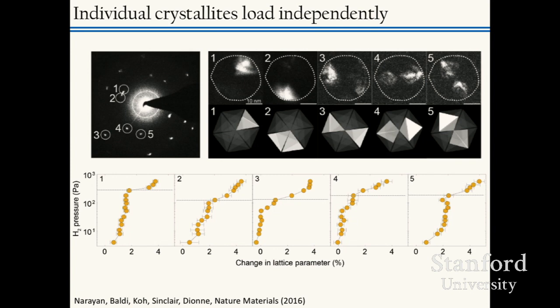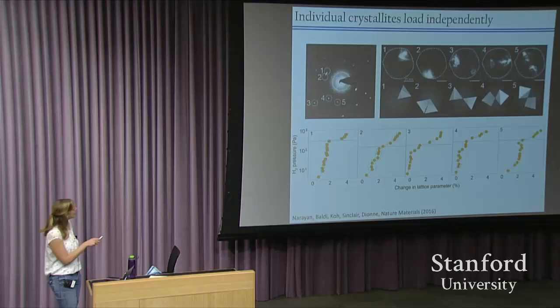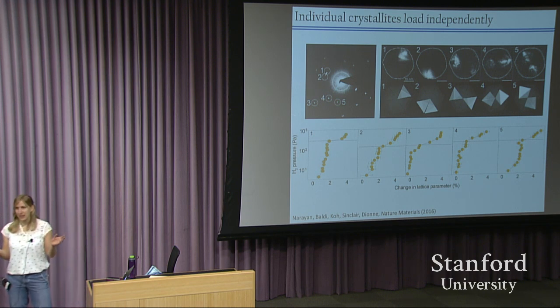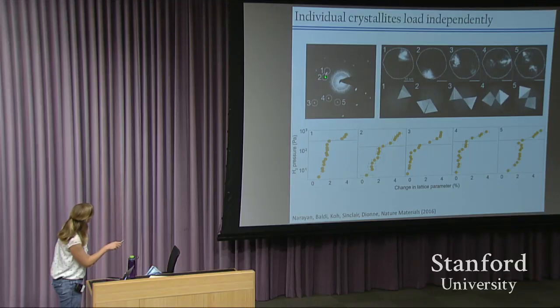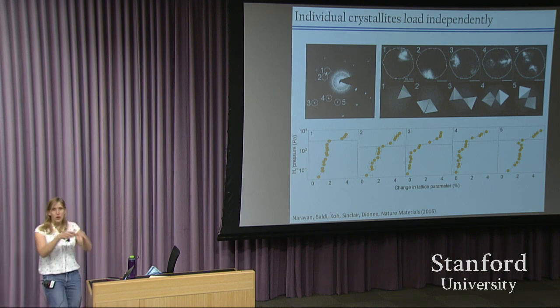Also, I mentioned that there were these sloped isotherms for the icosahedral nanoparticles, and we wanted to investigate that a little bit further, so we turned to diffraction and dark field imaging. Here what we do is we take a diffraction pattern of our nanoparticle, and we know that different spots in our diffraction pattern correspond to different crystallites in our nanoparticle. So what we can do is center our aperture over one of those diffraction spots and then image which part of the nanoparticle that spot was coming from. So for example, spot number one, which is very close to spot number two, corresponds to this particular tetrahedra within the icosahedra that's diffracting to that point.